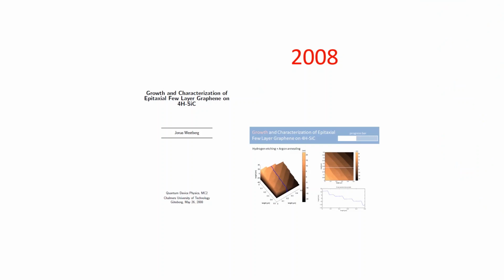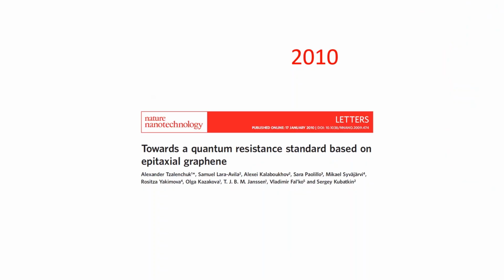And then we continued, and then we had master thesis studies and some other collaborations which continued over time. And then in 2010, we could actually demonstrate very high quality of the material, and it was demonstrated by quantum resistance. So the quantum Hall effect was very nice. And we had one of the nice papers in this journal. So usually from the materials growth point of view, it's very difficult to come into prestigious journals because you always need to demonstrate some application type of part of these things. But then we had really good quality of the graphene on silicon carbide.